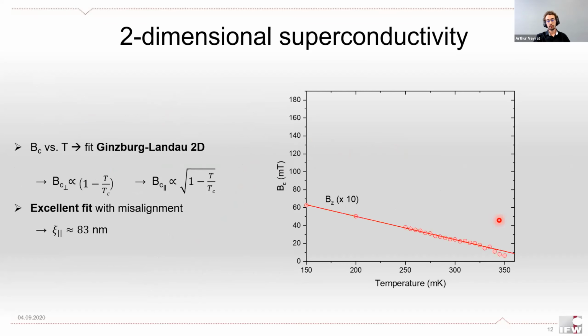If we want to study this further, we can look at the behavior of the critical field versus temperature this time. So here for the perpendicular critical field, we have a very linear behavior down to very low temperatures. This is expected for both the three-dimensional and the two-dimensional Ginzburg-Landau theories. But the three-dimensional Ginzburg-Landau theory expects also a linear behavior for the planar field, and this is not what we observed. We observed a square root dependency for the planar critical field, which is expected based on the Ginzburg-Landau theory for two-dimensional superconductors. So from these fits, once we take the misalignment into account, we can extract a planar coherence length of about 83 nanometers at 0 temperature, which is of the same order as what we had in bulk samples.